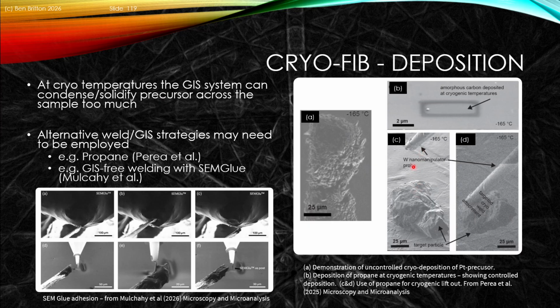And now you can effectively use this to cryo weld and attach in a very similar way to how we were doing the room temperature work. Other methods, as suggested by colleagues at Imperial College London, is the use of adhesives, SEM glue, to enable you to effectively attach the sample using this sort of glue structure to enable you to do the manipulation with posts for lift out, etc. in there.